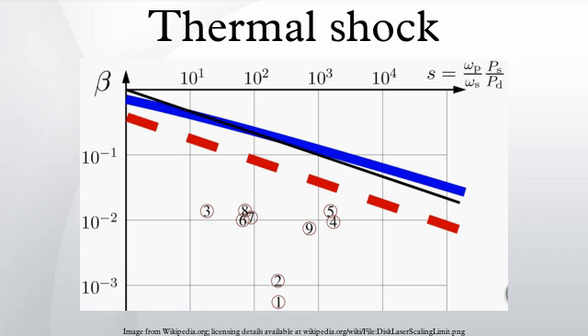Thermal shock parameter in the physics of solid-state lasers: the laser gain medium generates heat. This heat is drained through the heat sink. The transfer of heat occurs at a certain temperature gradient. The non-uniform thermal expansion of a bulk material causes the stress and tension, which may break the device even at a slow change of temperature. This phenomenon is also called thermal shock. The robustness of a laser material to the thermal shock is characterized by the thermal shock parameter.